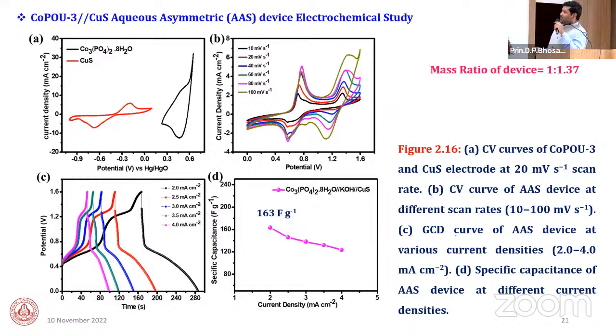Generally, in single electrodes we cannot measure beyond the 1.23 potential window because water splitting is observed there. But in the asymmetric device, we measured beyond the 1.23 potential window. How to choose this potential window: because of the sum of these positive and negative electrodes' windows, we can measure this asymmetric device up to this voltage range for CV and GCD also. The specific capacitance of this aqueous device is 163 farad per gram at 2 milliampere per centimeter square current density.